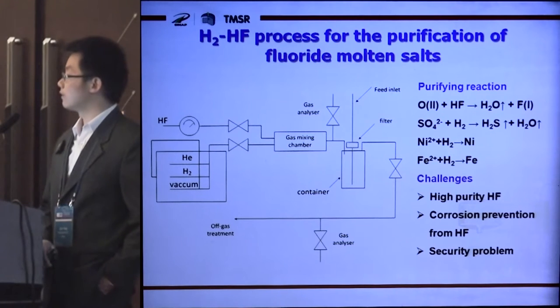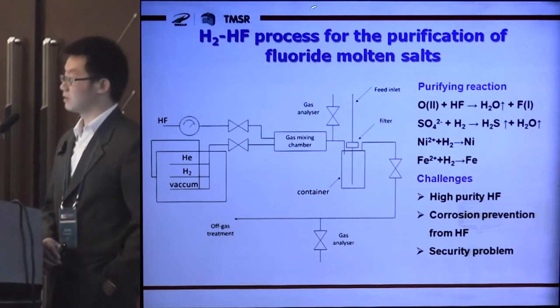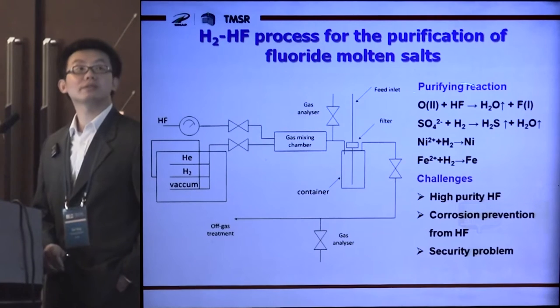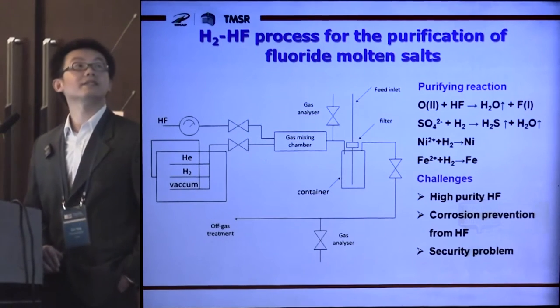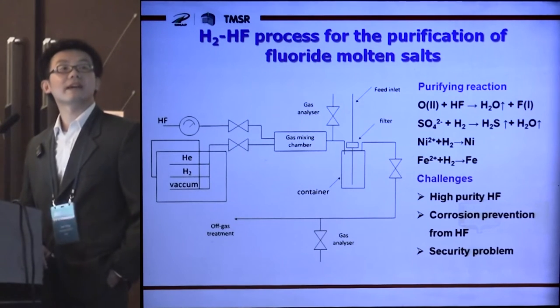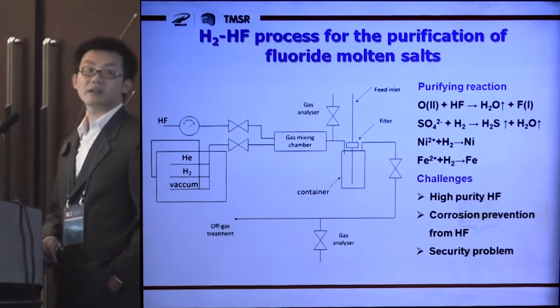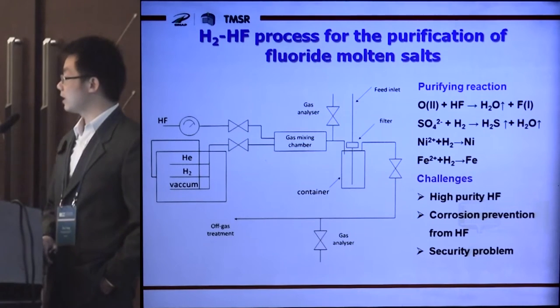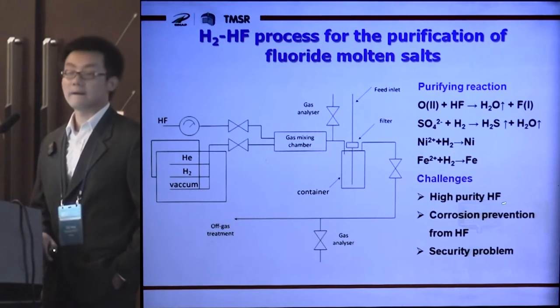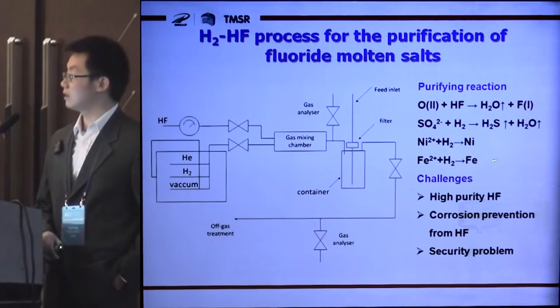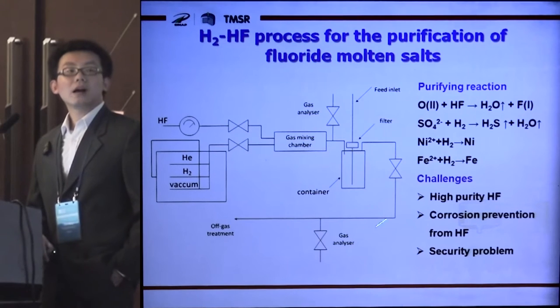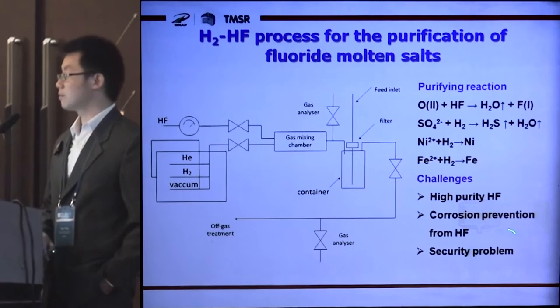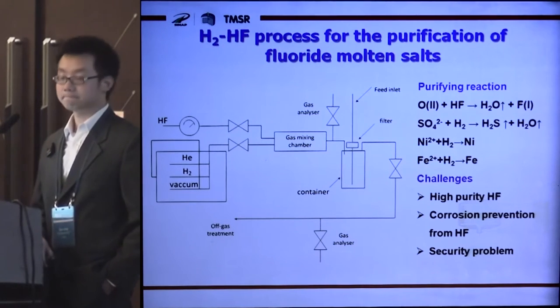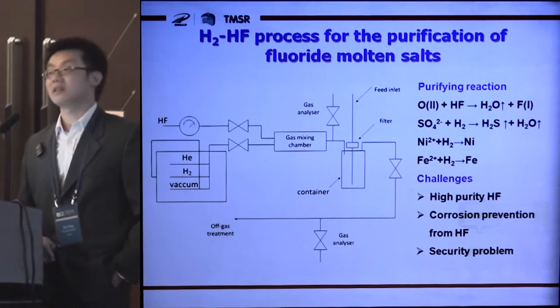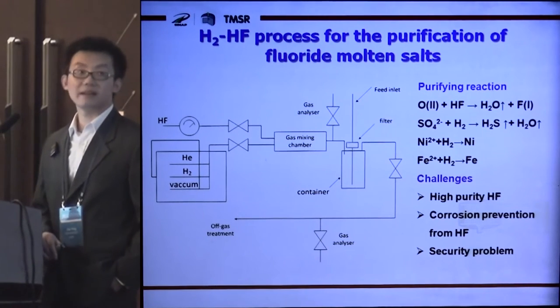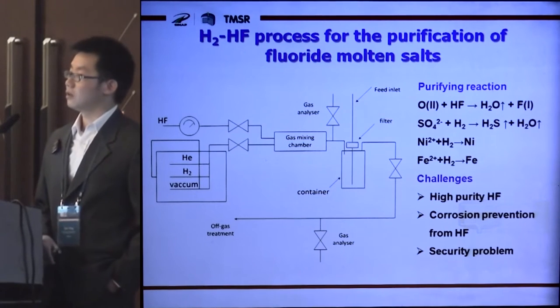The H2-HF process for the purification of the molten salt employed by MSRE is now carried out in our laboratory. Most of the oxidizing impurities can be removed by this process. From our experience, this process may face some challenges. For example, the industrial hydrogen fluoride may not be used directly because of the high content of water and sulfate in it. We must purify it before use. Other challenges like security problems and corrosion prevention from hydrogen fluoride should also be considered. These challenges then limit this process from acting as an online purification process, which may be needed in a working molten salt loop.